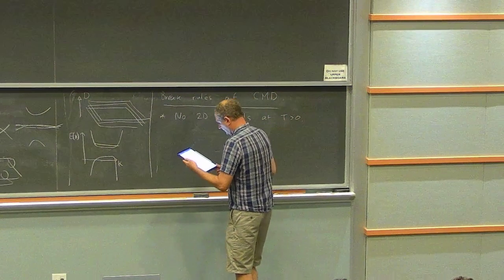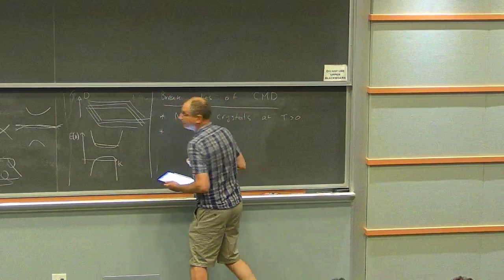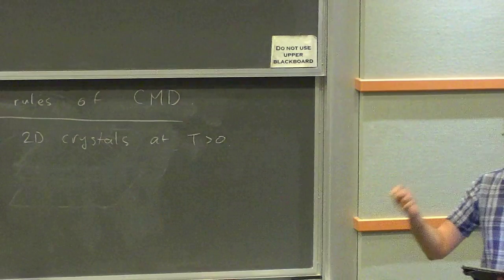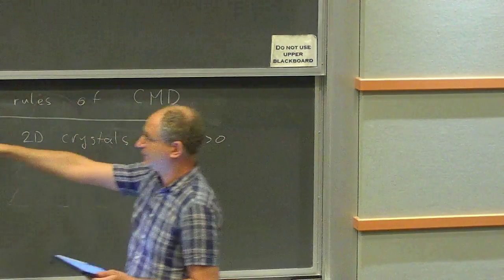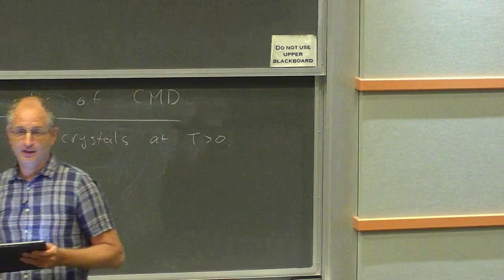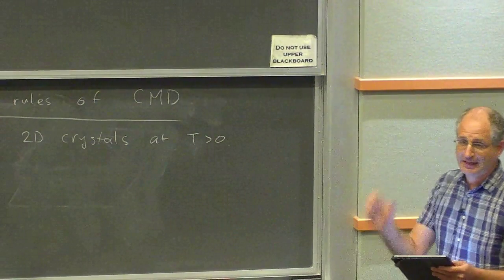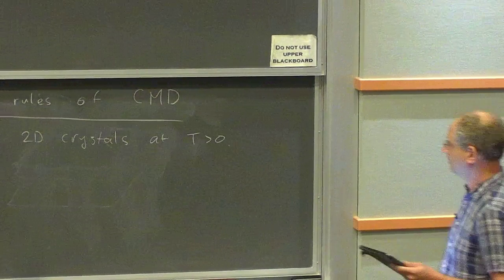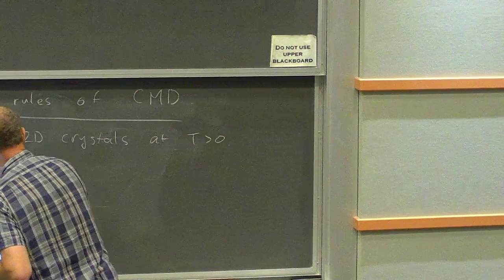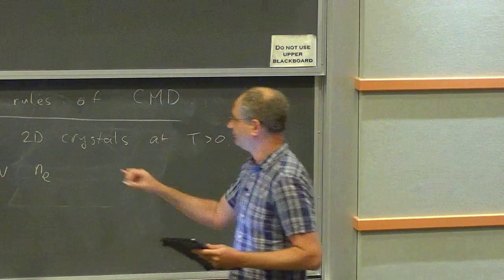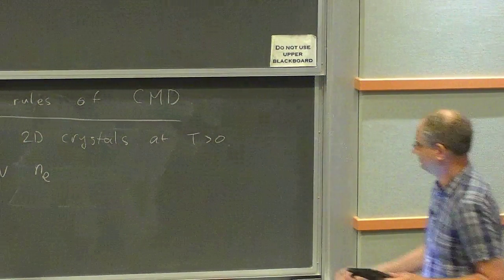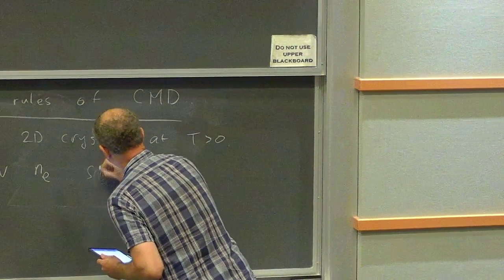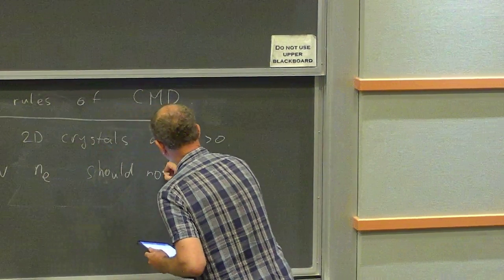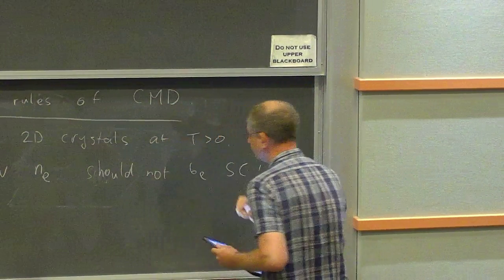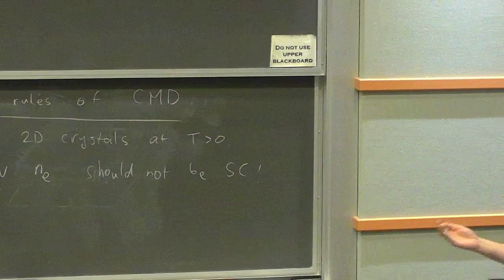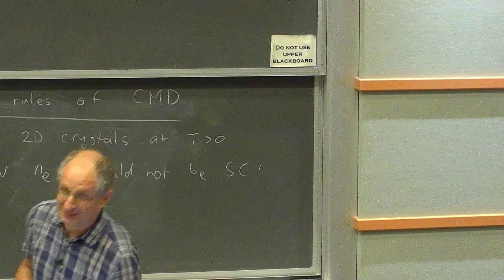So if we have a material that has a tiny concentration of electrons, if we think about either of these 2 materials, the distance between 2 electrons is hundreds of times the lattice spacing between the atoms. So low carrier density materials, systems with very low density of electrons, shouldn't be superconducting. There are many ways to see this. We would say, well, if there are no electrons, clearly this is not going to be a superconductor.